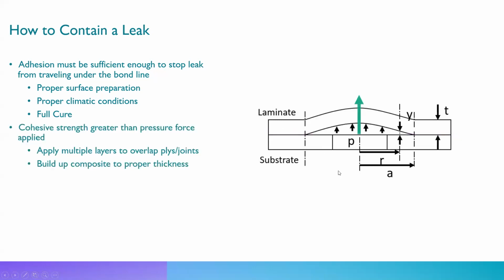Next thing we want to look into is that the cohesive strength is greater than the pressure force applied. So whatever we put on top of the hole, we want to make sure that the pressure can't just go through it. The way we achieve this is by applying multiple layers to overlap plies or joints and to build up the composite to the proper thickness. So with our ASME engineered wrap, we can actually calculate how thick it has to be to hold in the pressure coming out of the hole.